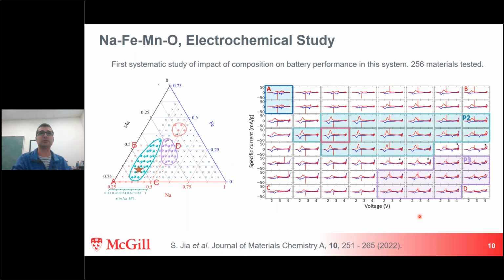Okay, so here goes. What does this look like? The ternary diagram has sodium at this corner, iron up here, and manganese down there. And prior to our work, we knew from other literature that there were two materials up here in a phase called P2. So the phases in sodium ion batteries just talk about the ways that the layers are stacked. And it has some impact, but really what we want is to make a single phase layered material and screen the battery performance. So there were two materials known to be up here and one down here.